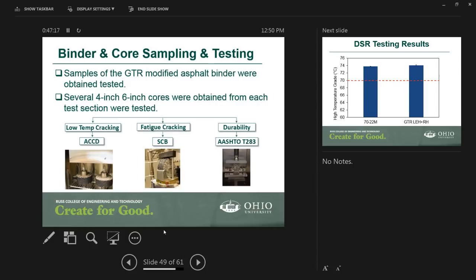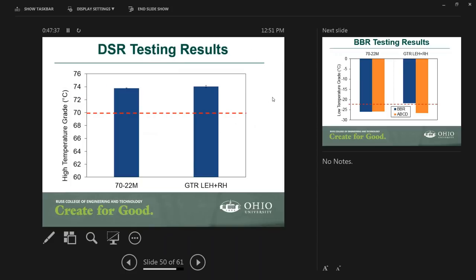And we did the same tests that we have done before for the Columbus core samples: ACCD for low temperature cracking, SCB for the fatigue cracking, and then for moisture susceptibility, we used the AASHTO T 283. High temperature grade, in both cases, it met the 70 degrees. The GTR had slightly higher, but not much.